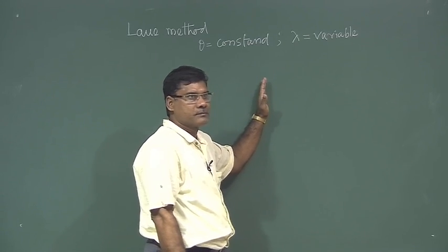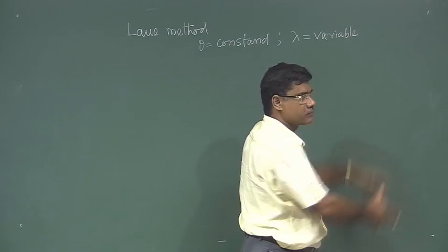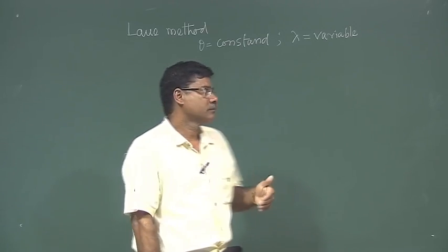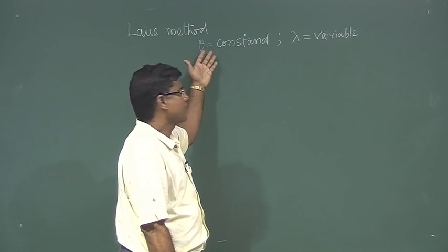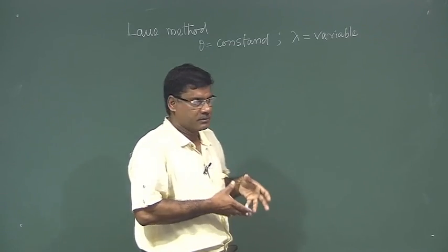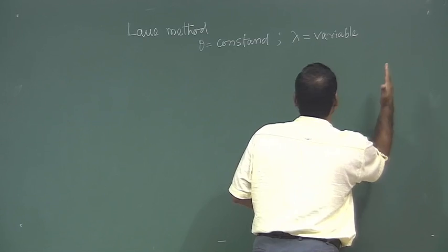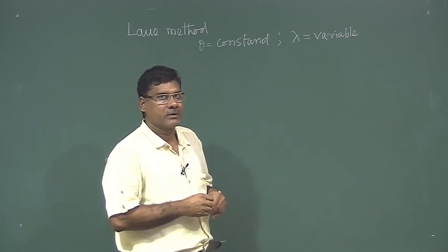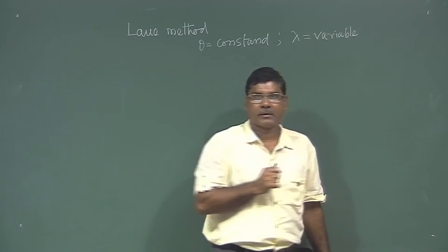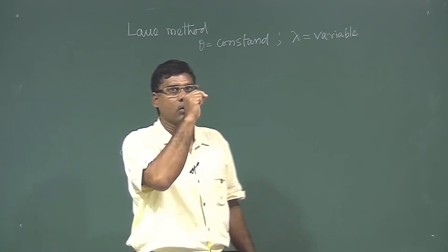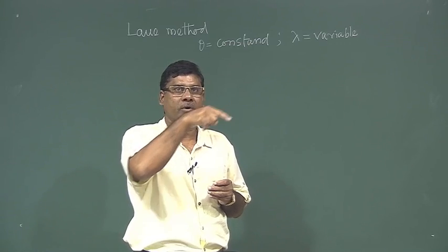from the crystal, for a particular angle, the diffracted rays are on a cone. For a different plane the angle will be different, and each particular plane will form a cone. Those are concentric cones, and if I place the screen or X-ray plate, these diffracted points will be on that X-ray plate. So, they will form a spot on that plate.